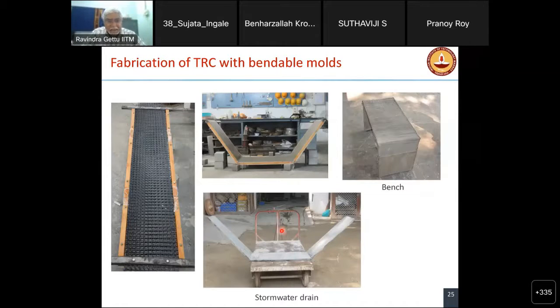Here, this is an element where we have tried to bend in the fresh state. So if you want, say, a stormwater drain section, or you want to make some bench like this, what we have done is you make a mold like this, pour the concrete, and then when the concrete is fresh, you make sure that the mold can bend. So then you get the section that you want. And then you finish it off. So this means that we can prefabricate elements like this by appropriately engineering the mold and using the mold to give you the element you want.